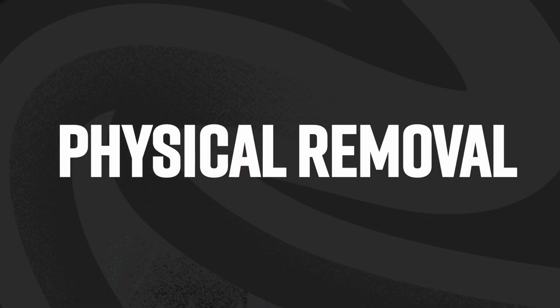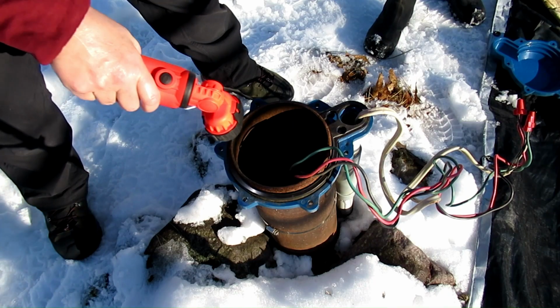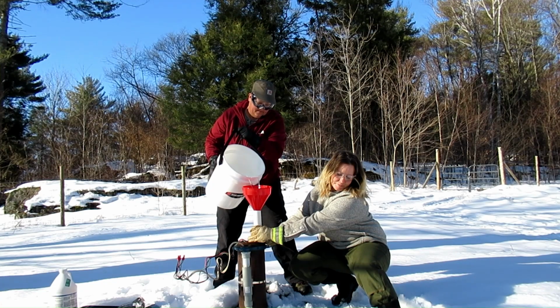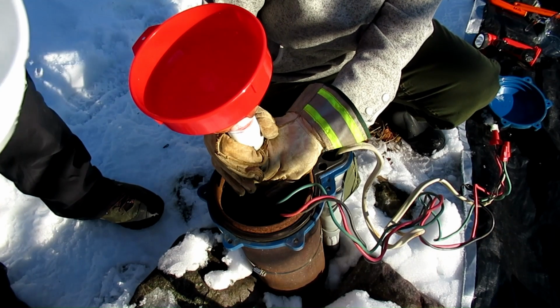Now let's look at the toughest iron issue to deal with, iron bacteria. This type of bacteria doesn't just cause clogging issues, it's also highly resilient, making it tough to remove. Physical removal is typically the first step in very infected wells. It's highly recommended to work with a licensed well contractor who will physically scrub to remove the biofilm buildup from inside both the well casing and the pumping equipment. The next step is to shock the well with chemicals to disinfect it. This process involves adding a high concentration of chlorine directly into your well, which will kill existing bacteria and help to prevent future growth. It's important to ensure that the chlorine solution flushes both through your well system as well as your home's plumbing for optimal effectiveness.